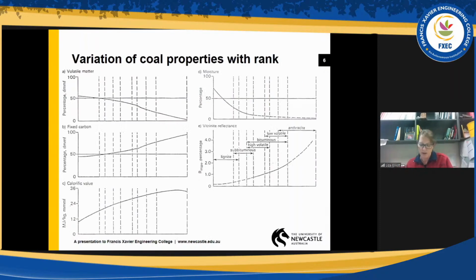As you become more coal-like, or the rank of the coal increases, you're going to lose things like moisture. You're going to lose the volatile content, and that's the stuff that will come out of the coal when you heat it. So those are the low molecular weight hydrocarbons, the things that are hanging off the side, and the things that bond between the aromatic rings. You're also going to increase your fixed carbon content. This is the actual rings, the carbon in the rings that you've got in your coal. That's going to increase as the coal becomes of a higher rank, and the actual energy associated with your coal will increase as well.